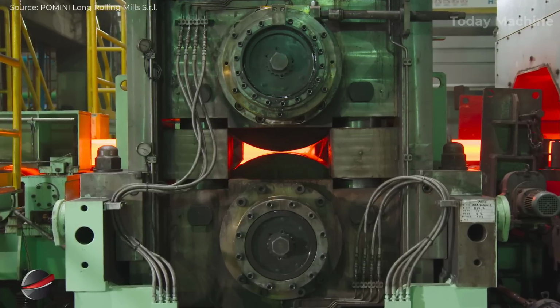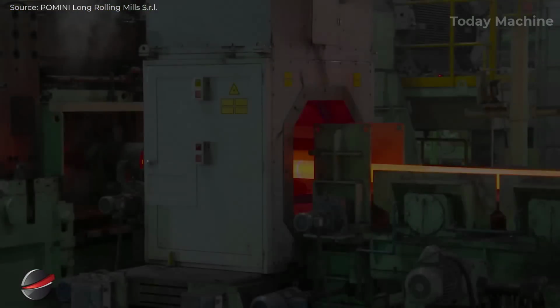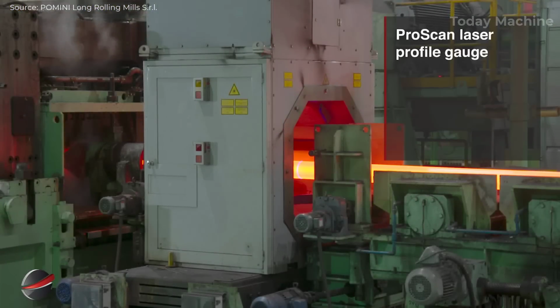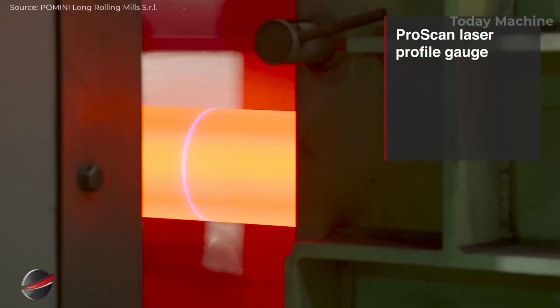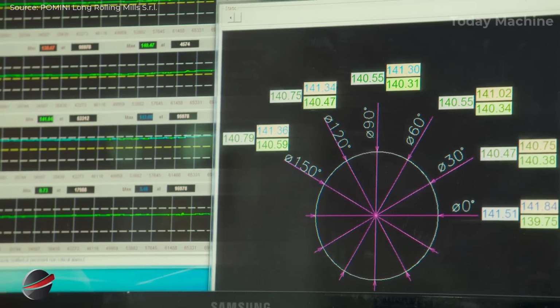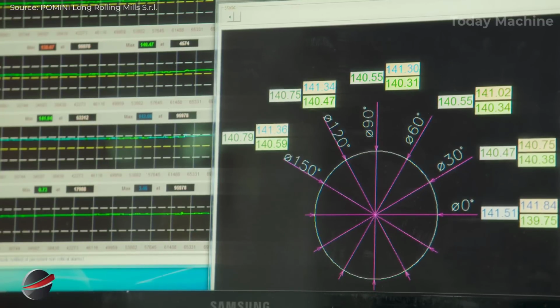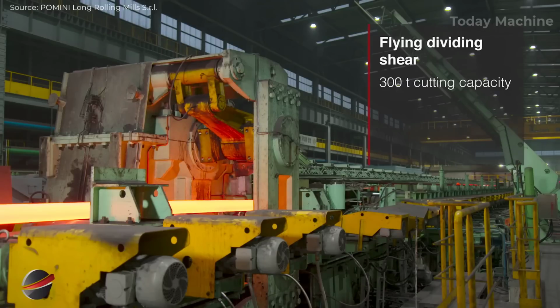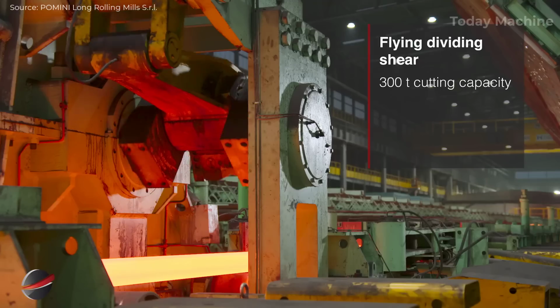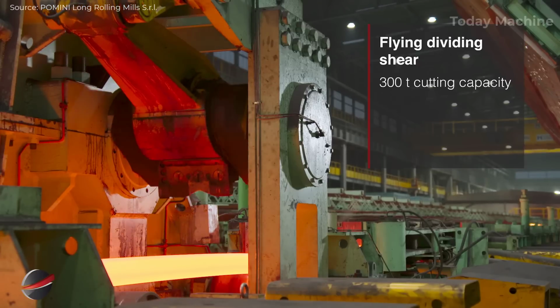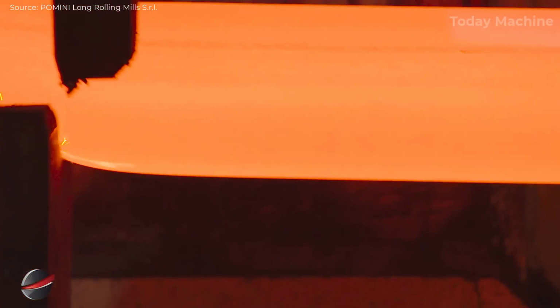The large bar mill at Hyundai Steel produces round bars in sizes ranging from 80 millimeters to 350 millimeters in diameter. After the initial reheating and descaling processes, blooms are reduced to round bars using the breakdown mill and the continuous finishing and sizing stands. A ProScan laser profile gauge ensures the bars meet precise dimensional standards.